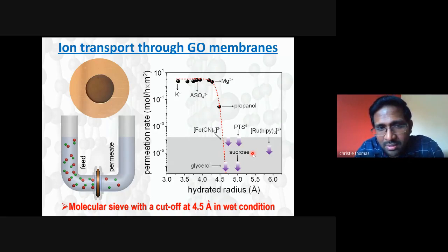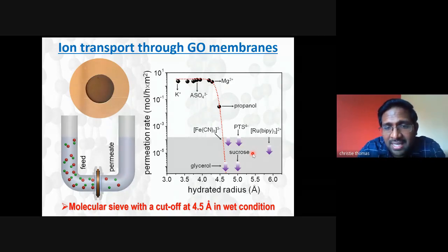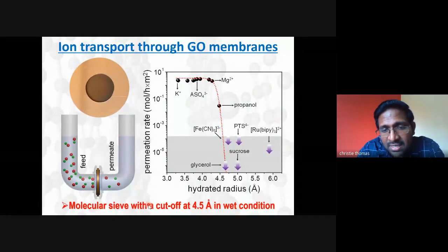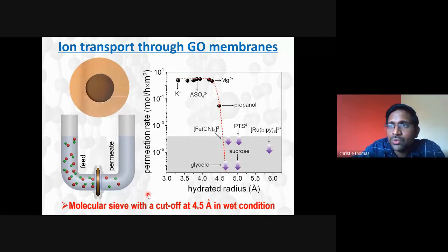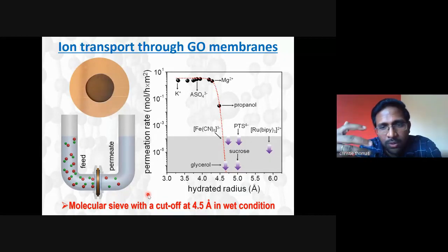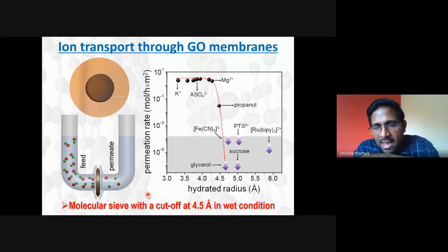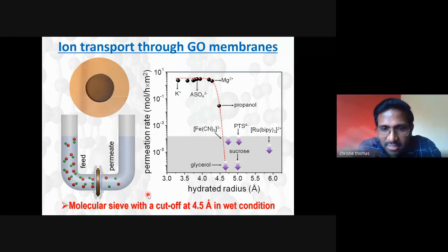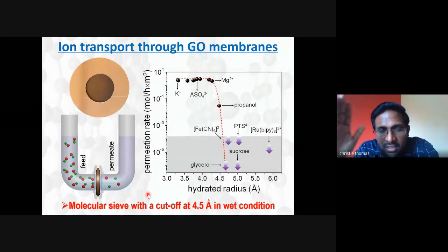Okay, so what does it mean? It means that graphene oxide can act as a molecular sieve with a cutoff at a hydrated radius of 4.5 angstrom. Molecular sieve means like a sieve you use for filtering your tea. So graphene oxide can act as a sieve with a cutoff at 4.5 angstrom in wet condition. All the molecules having a hydrated radius greater than 4.5 angstrom will be cut off.